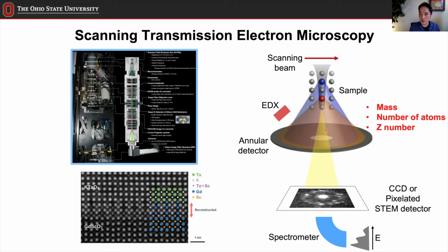Among these many kinds of signals, the one signal that we're relying on is what we call the annular dark field signal, which is collected by this donut type detector. If you see this schematic diagram, the donut is covering the high angle scattering area, meaning these are the electrons that are scattered at relatively higher angles. And this information is in fact very important, because that scattering information is mostly related to the Z number of the constituent atoms, and also their numbers.